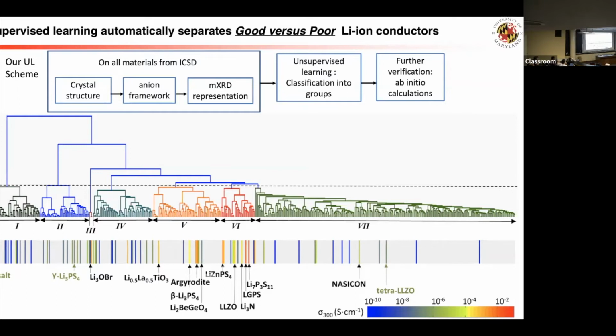For each material, we look at whether there's already a known lithium conductivity property, because that's from experiments, and we plot it as a color bar down here. The red color is high conductivity, which is what we want, and the colder color is low conductivity. What we find very interesting is that this unsupervised learning can indeed classify these good materials and cluster them into these two groups, group 5 and group 6.